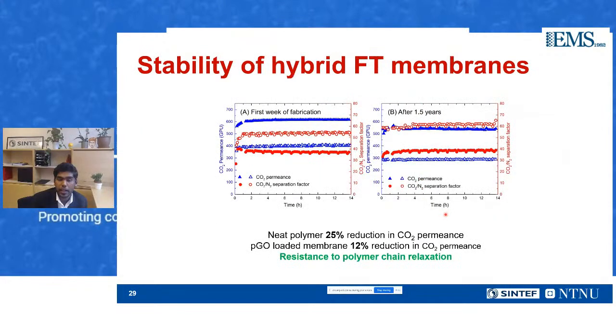So we subjected this 0.28% loaded graphene oxide to a condition where we wanted to test its durability for CO2. We stored the membrane for about 1.5 years and then checked the CO2 permeance and selectivity. Usual polymeric membranes tend to have reduced performance due to chain relaxation of the polymers, which is very natural when it's not operating.